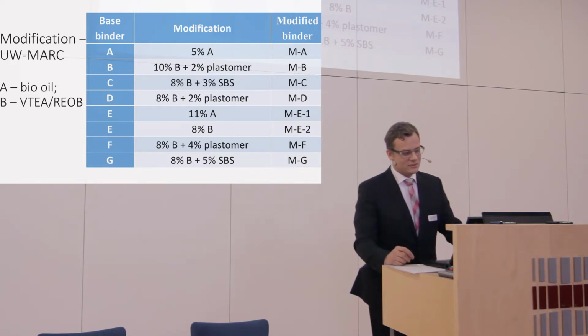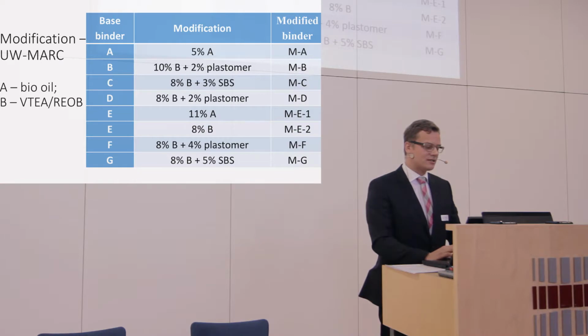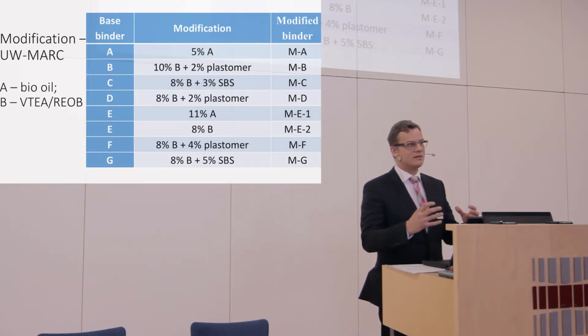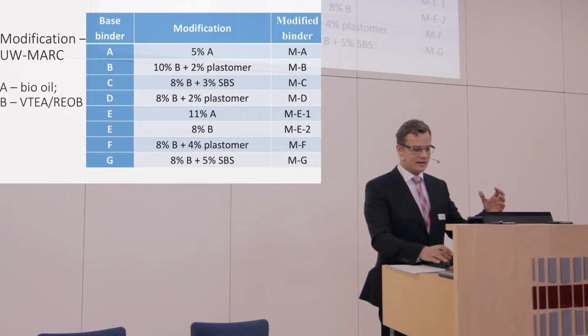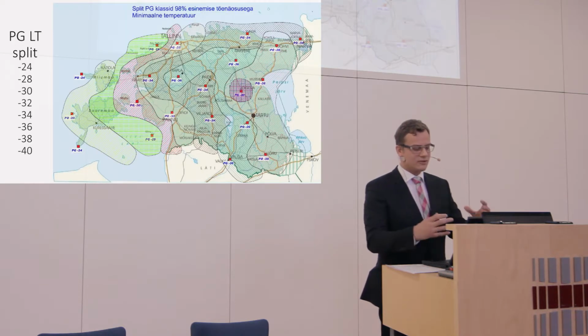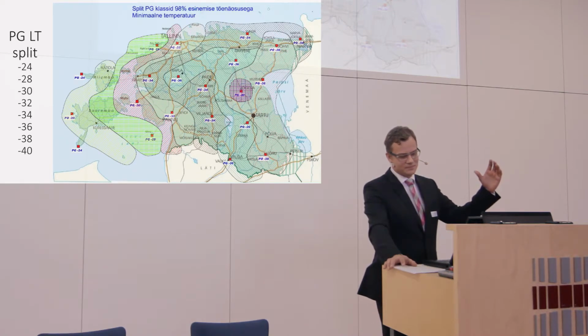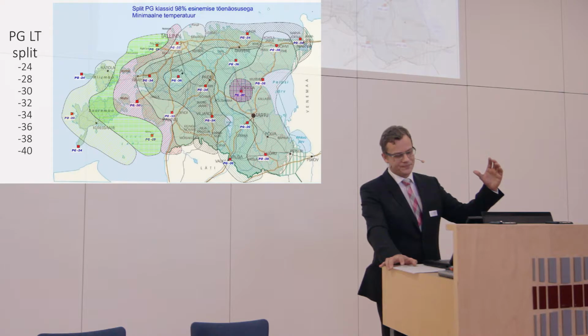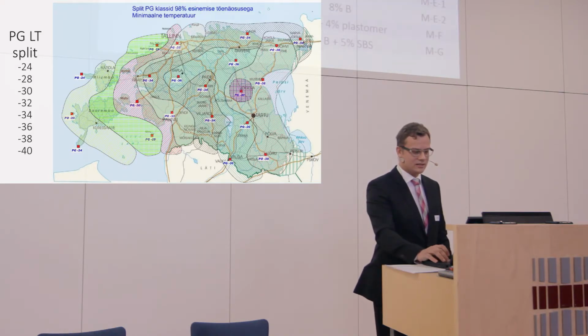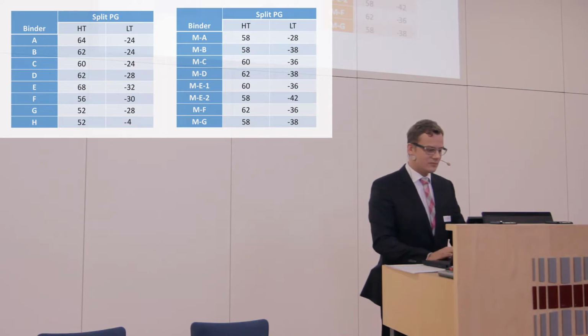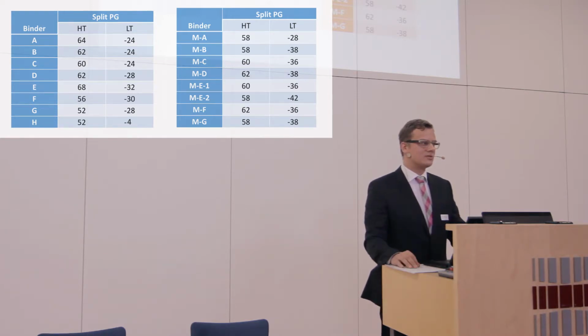Now, what this waste engine oil and bio oil does is make bitumen less viscous. Thanks to this, we can reach lower degrees with our bitumen, and you can see the results over here. So before you had -24 here, now you have -28. But for example here, before it was -28, and now after modification it's -38. And as you can see, thanks to modification with polymer, we don't lose in high temperature properties either.